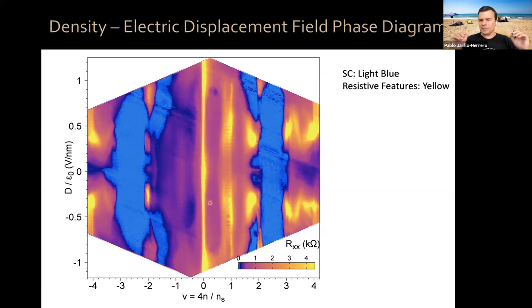So that tells you that the bottom twist angle and the top twist angle, between layers 1 and 2 and between layers 2 and 3, are very similar, okay, or probably almost identical, because otherwise you would see an asymmetry when you polarize your carriers with your displacement field. Now, the other thing is that it becomes something of a half full, half empty glass of water. You can think of left and right as having a lot of symmetry, or you can focus on the asymmetry, okay? There is certainly some symmetry.